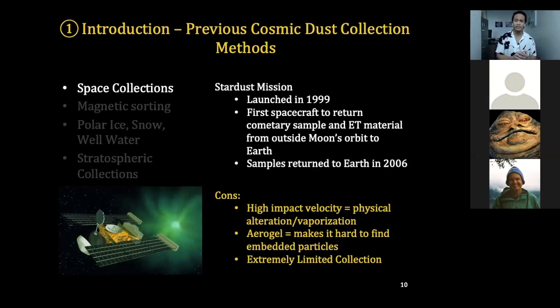This high impact velocity can then cause physical alteration or sometimes even a complete vaporization of these particles. To combat this issue, these types of missions use a material called an aerogel, which acts as a cushion and an adhesive to hopefully preserve that particle. What ends up happening, however, is that these particles end up embedding themselves deep inside this aerogel material, causing them to be hard to locate.